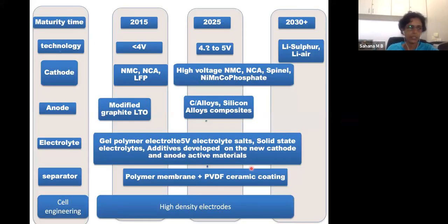So the overall research that needs to take place for complete solid state batteries is this roadmap. With the technology, the first will be increasing the voltage by 2025. The voltage of the cells can go from 4.2 to 4.5 volts. And then instead of lithium ion batteries, maybe moving to lithium sulfur and lithium air. And in the cathode, the materials can change in this way. And the electrolyte can move from gel polymer electrolyte to complete solid state electrolyte.